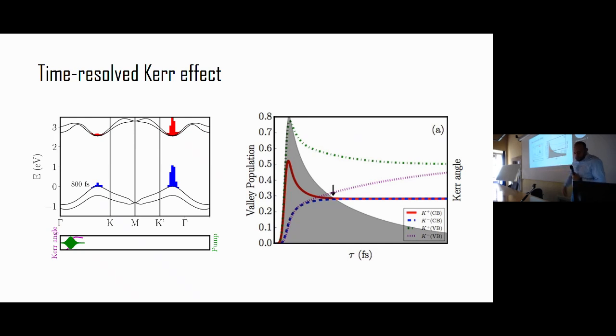So basically, imagine that you excite an exciton with the light, but when we propagate these, let's say that we do the following trick. We put our exciton excitation in the energy level of the electron and the holes, no? And then electron and holes disperse as electron and holes, not as a bound exciton, for example. This is one of the critical approximations. Why is that? Because we still don't know how to propagate an exciton-phonon, or at least not as efficiently as you propagate an electron and hole.